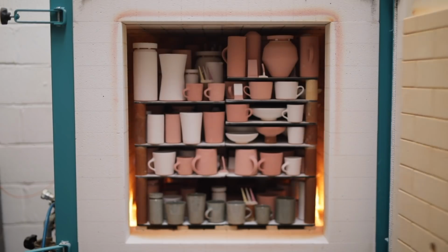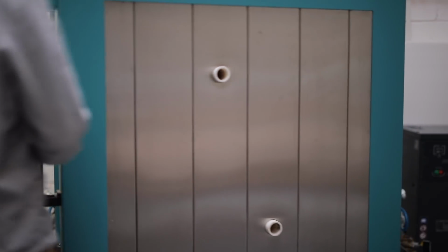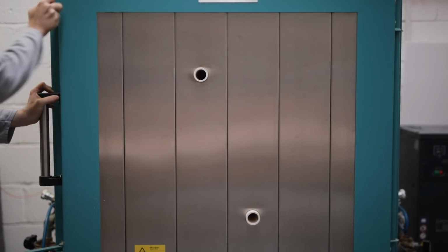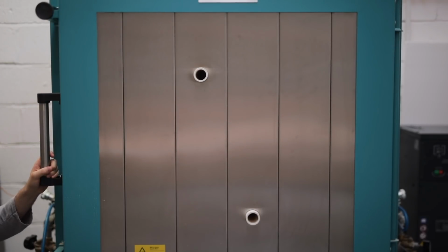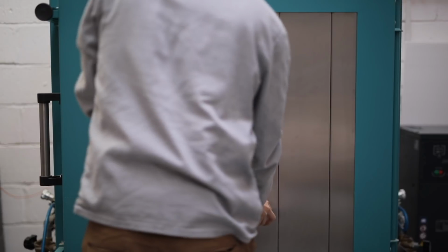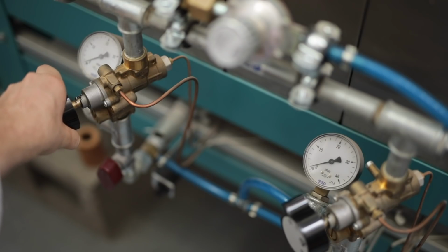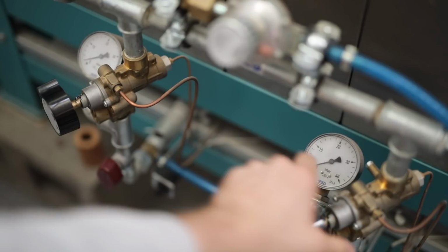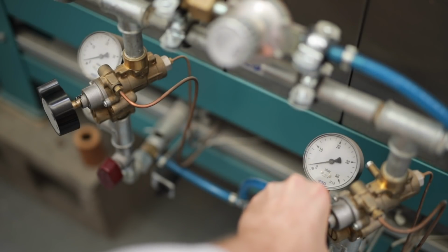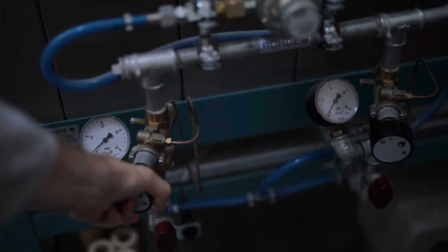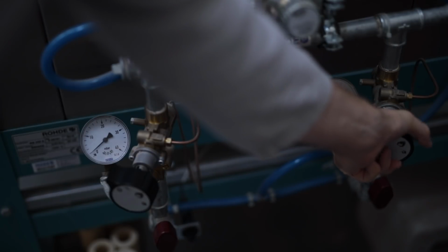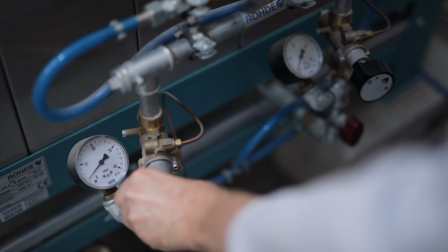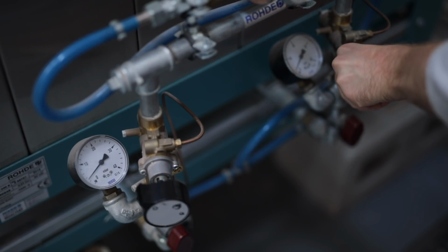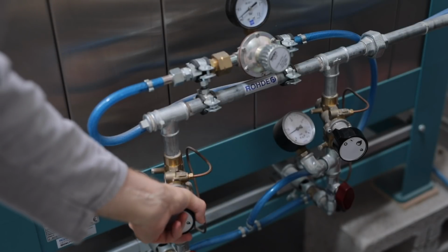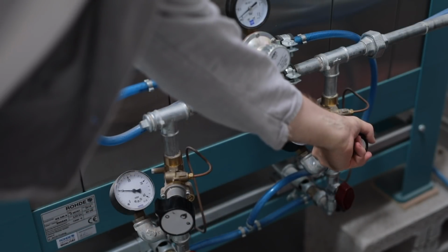Once all 4 burners are fully lit, I close the door and tightly seal it. I also place the 2 bungs into the spy holes, and I also make sure that the damper, which covers the flues of the kiln, which lead up to the chimney, is mostly open. Thereafter, over about a 4.5 hour period, I slowly increase the gas pressure so that the temperature climbs higher and higher. At exactly 860 degrees Celsius, I set the kiln into a reduction atmosphere.